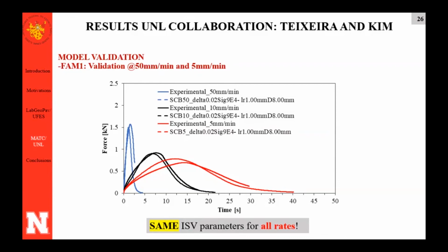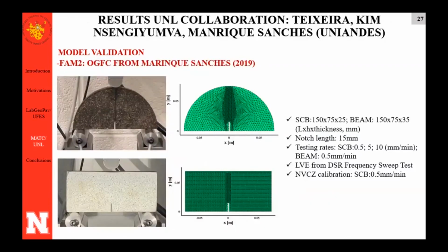But one sample, one material is not enough. Let's see if this works with a different type of sample. My friend Laura had a test done here in UNL, with a sample that was obtained from an open graded friction course mixture, totally different mixture composition than the previous one. And she did two tests, SCB test and beam tests, okay?